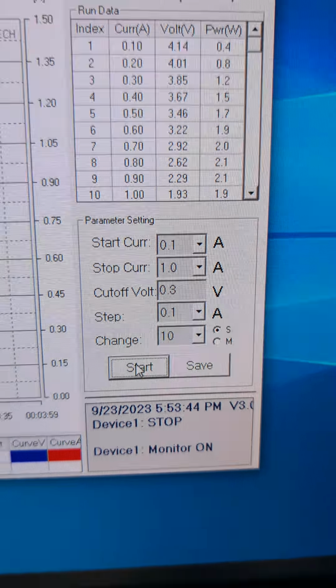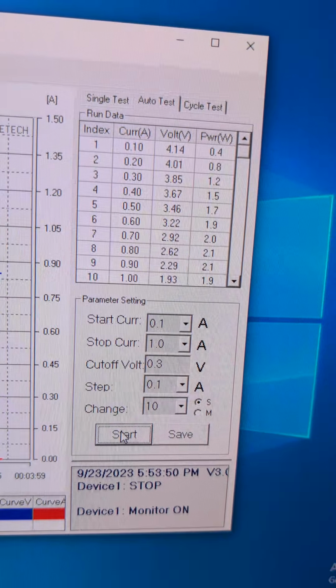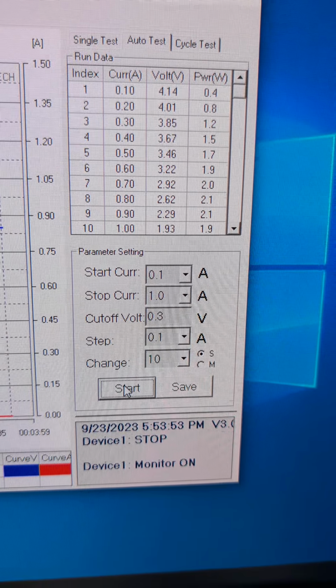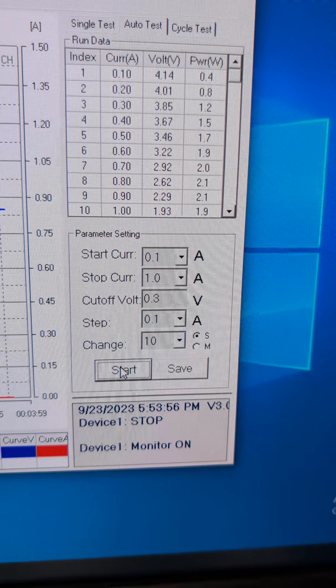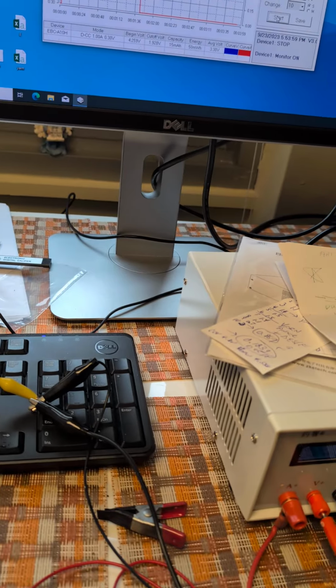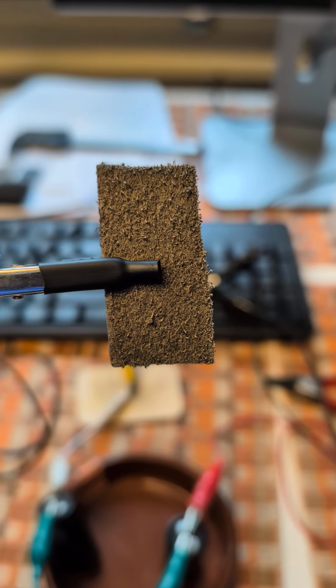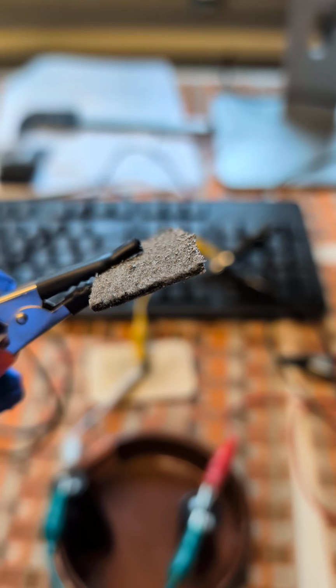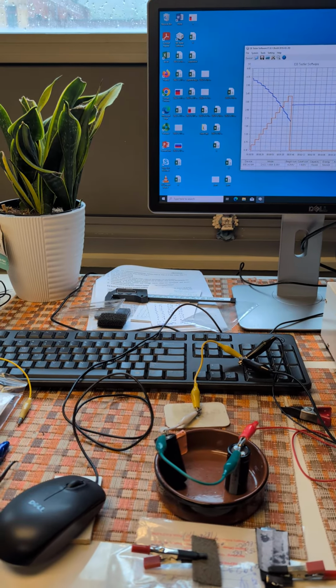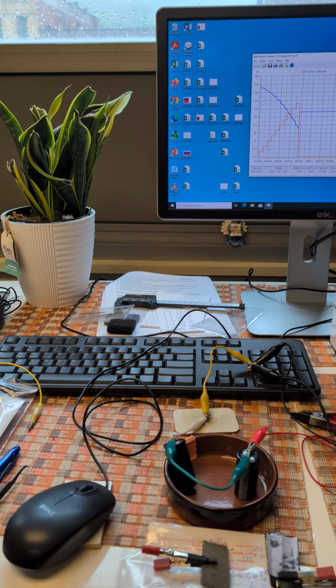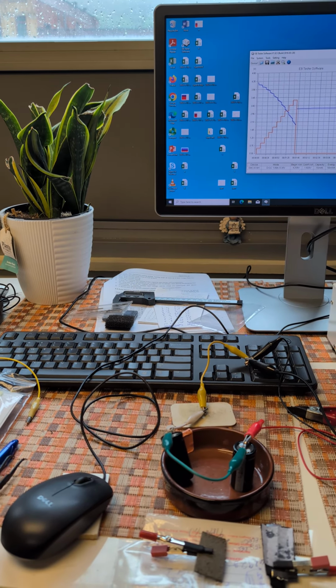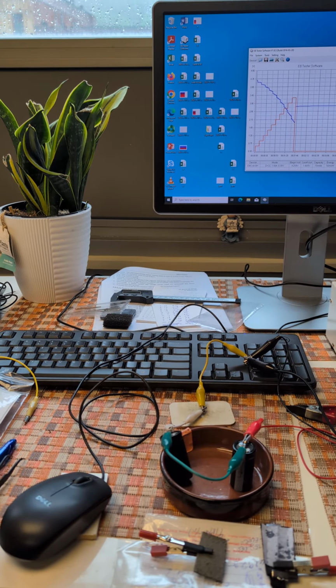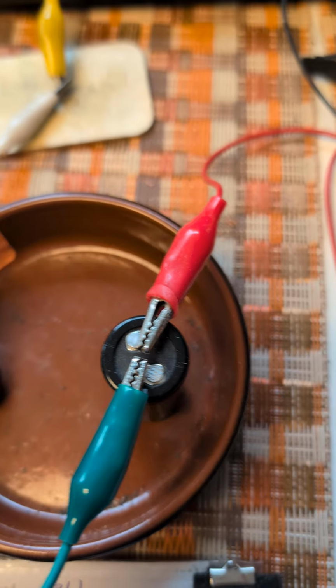And you could see that with the caps themselves, we had 3 2.0 or higher and a couple of 1.9s. And you saw that with the nickel-plated graphite, we were starting to take on a semblance of solid conductivity. The graphite felt without treatment, commercial graphite felt that I use, and there are different thicknesses, of course. We get 0.9 ohms per centimeter with a multimeter, and it's good enough that it can serve as a conductive material. And of course, I wouldn't recommend using alligator clips.